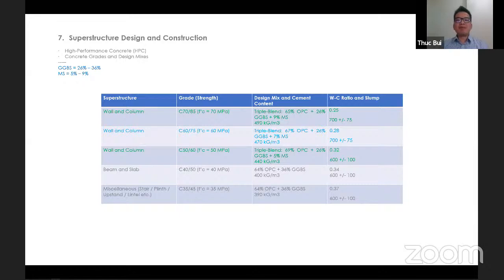We also use high performance concrete for the superstructure. We also use triple blend for the vertical elements. The percentage of GGBS is between 26 to 36%, and microsilica between 5 to 9%. We maintain also a low water cement ratio, as you could see on the chart, and a very high slump. They are mixes that we've been using for most of our tall buildings in the UAE. Those mixes had a great workability for pumping up to more than 300 meters.